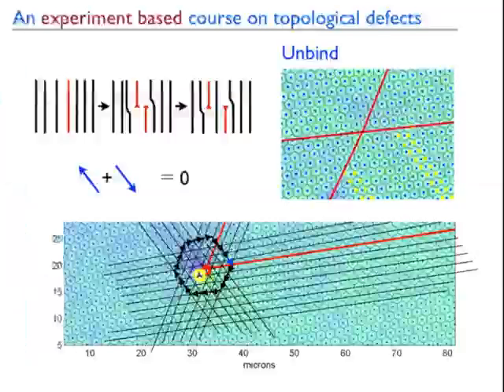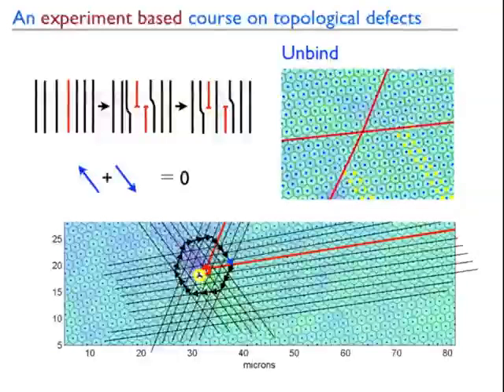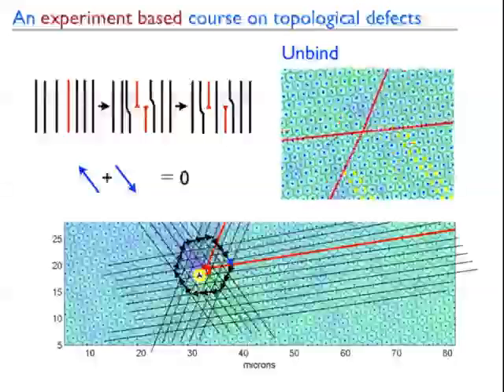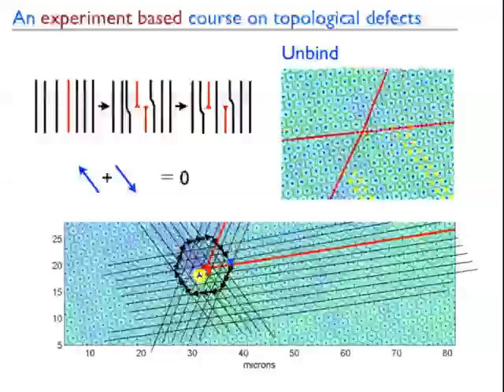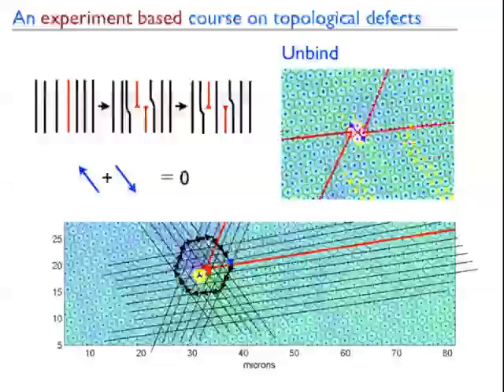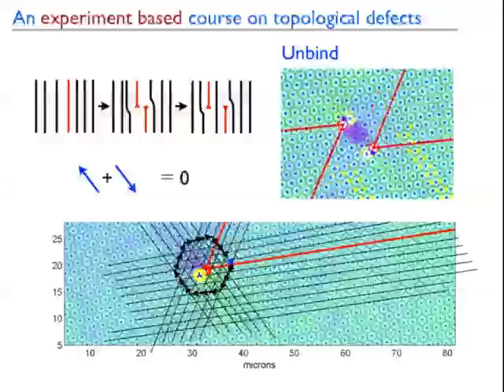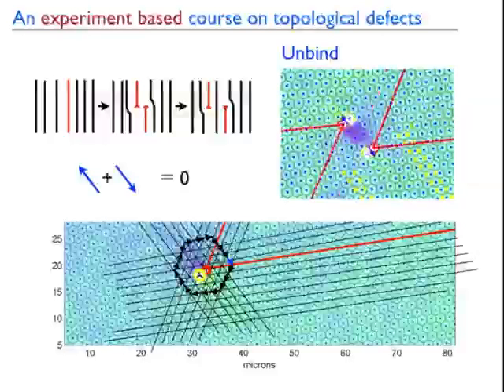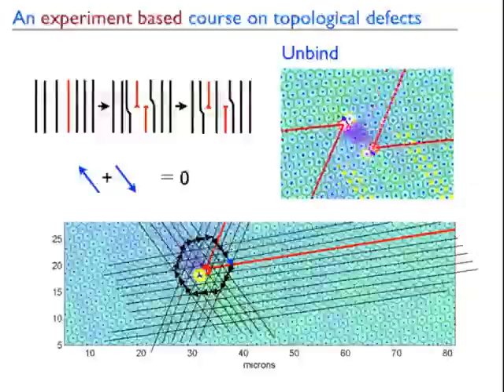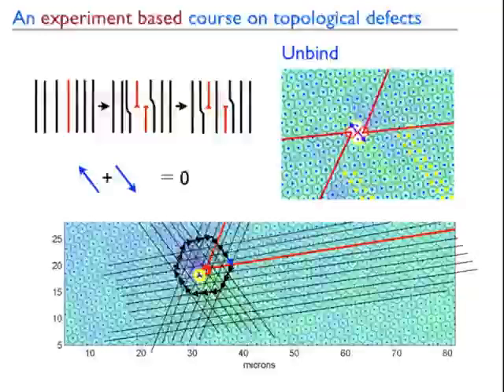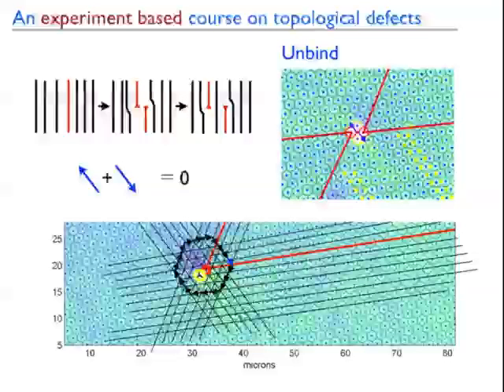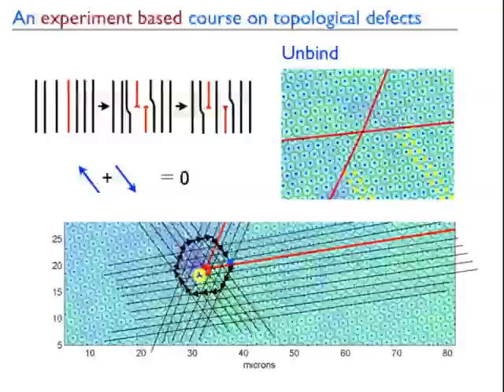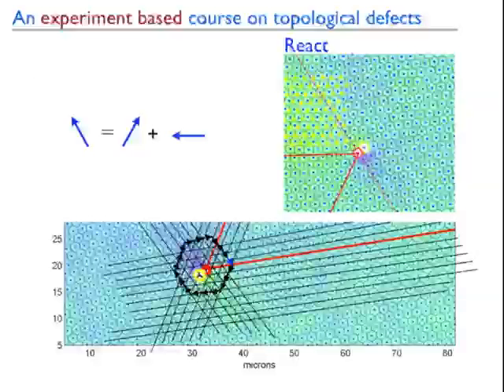With optical tweezers, we can do other things to these. For instance, I can just take the crystal and strain it. If I strain it enough, I can take this region, which is a perfect crystal, and this was in the first slide as well, and I can create from it 2 dislocations. Now, topological systems not only have this property, they have conserved quantities. If I start out with no dislocations in the system, no Burgers vector, I have to get the sum of them to cancel if I create 2 of them. So here I have to create 2 opposite ones. That's what I'm doing over there.